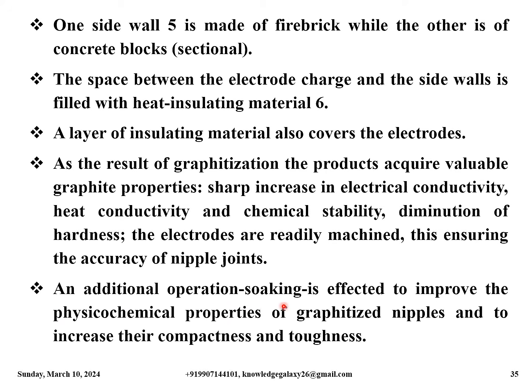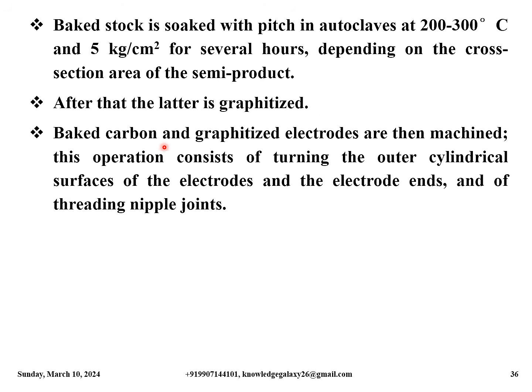An additional operation, that is soaking, is effected to improve the physico-chemical properties of graphitized nipples and to increase their compactness and toughness. Baked stock is soaked with pitch in autoclaves at 200 to 300 degrees Celsius and 5 kg per square centimeter pressure for several hours depending on the cross-section area of the semi-product. After that, the latter is graphitized. Baked carbon and graphitized electrodes are then machined.